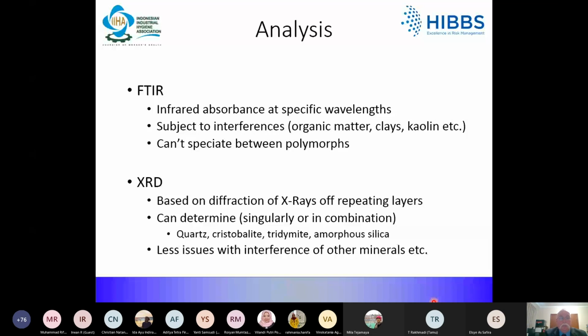Now, X-ray diffraction suffers less from interfering materials than does infrared, but its most significant advantage is it can differentiate between the various crystalline silica polymorphs. And if you suspect that both quartz and cristobalite polymorphs may be present, then XRD has to be used. FTIR will give you incorrect results.